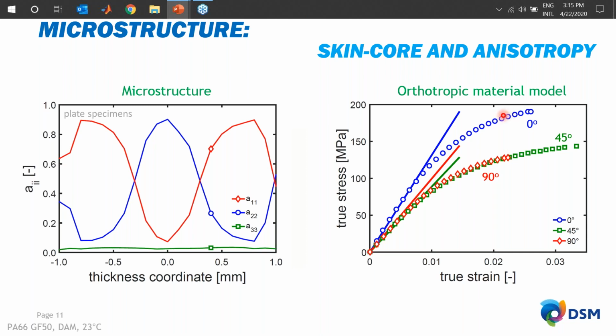On this stress strain data, you can fit, let's say, linear elastic material properties. So all the fatigue simulations are done using a linear elastic material model, as I'll demonstrate in a second. So we capture the orthotropic material properties using these stress strain curves. And then eventually we fit, using the stresses that we compute on the tensile bars, the failure indicators, which are the strength directions in either the in-plane direction, perpendicular, or the shear direction.